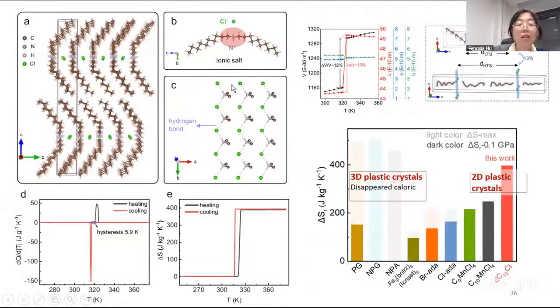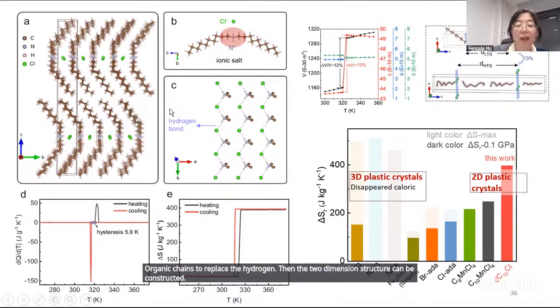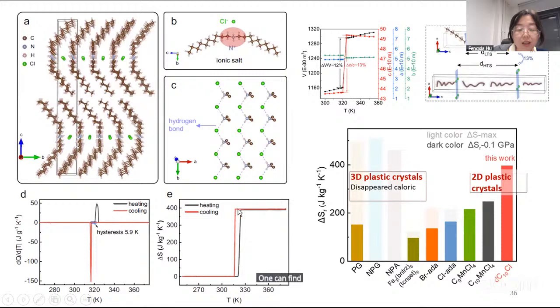This is the structure of the molecule. Originally, the nitrogen atom is bonded with 4 hydrogen. On the left and the right, we use organic chains to replace the hydrogen. Then the two-dimensional structure can be constructed. One can find the entropy change still remains large, but the hysteresis loss can be reduced to about 6